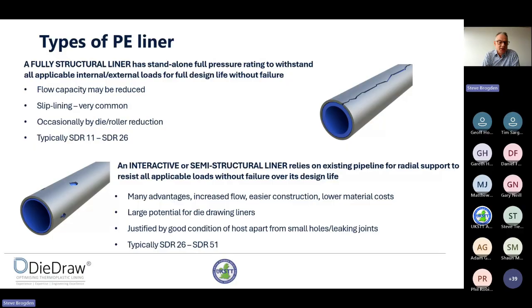Another type of liner is an interactive or a semi-structural liner, where we're utilising the hoop strength of the host pipe, and we can justify a thinner liner than the pressure rating. For example, we use an SDR 51 in Stockholm, operating at 10 bar. There is a methodology that exists where we can determine the strength of the pipe for bridging holes over 50 or 100-year lifetime. So the approach is we go to the water company and say, this pipe could withstand, say, a 150 millimeter diameter hole in 100 years' time, if we're putting in something that's less than the pressure rating. So there's a very effective methodology there.